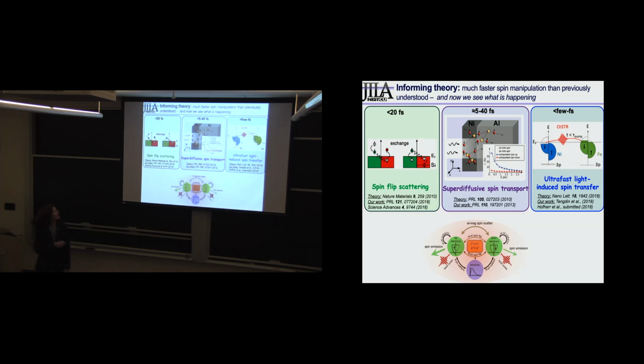So it turns out that we've looked at a number of different materials, and through our collaborators also, and essentially in all these materials we see much faster spin manipulation than we understood before. This is the spin flip scattering that we think underlies the nickel work, that essentially exchange scattering can happen, and we've measured that using other techniques. We've measured not the exchange but the spin conserving scattering process, and it does indeed, depending on the electron energy, can be super fast. This is the direct light-induced spin transfer that's going on in the Heuslers,